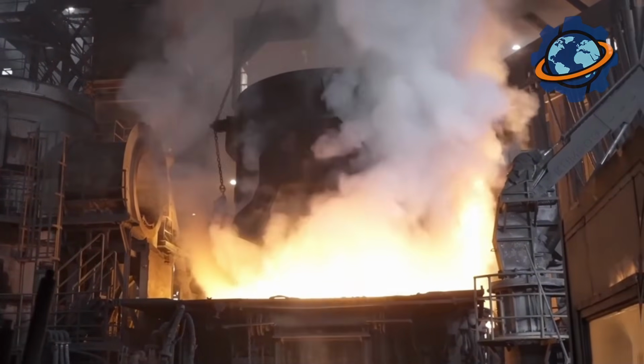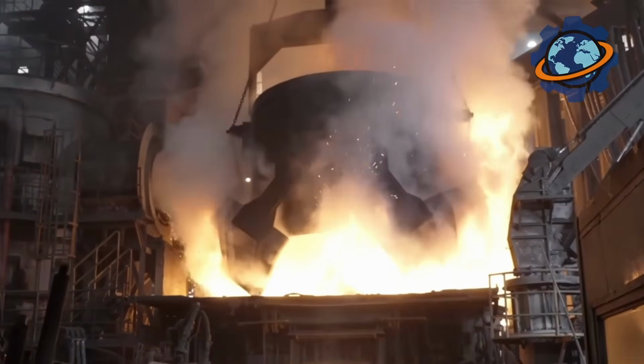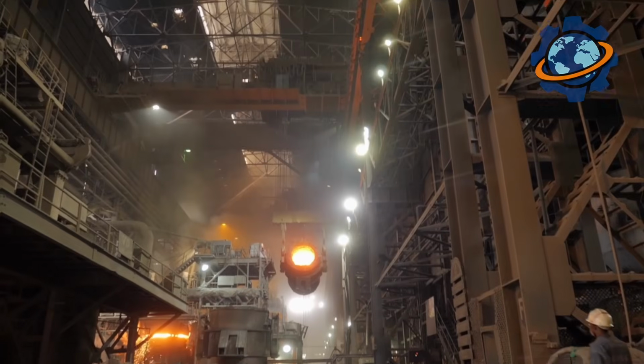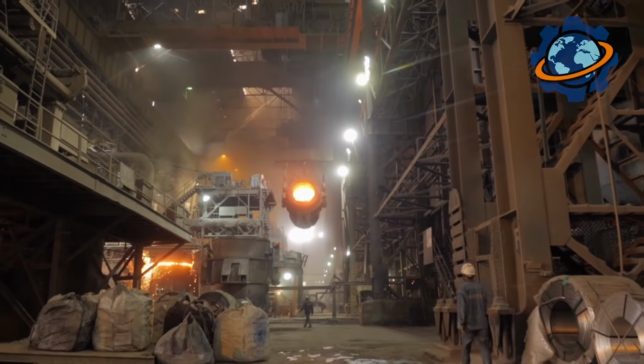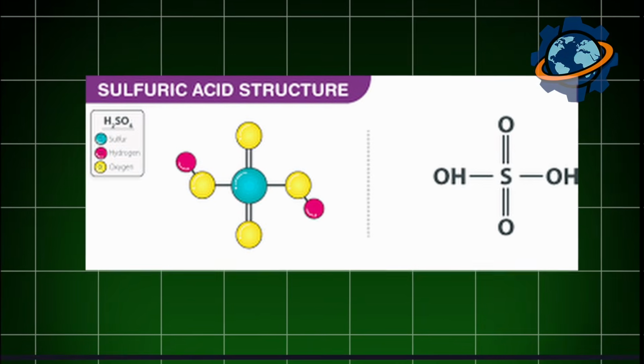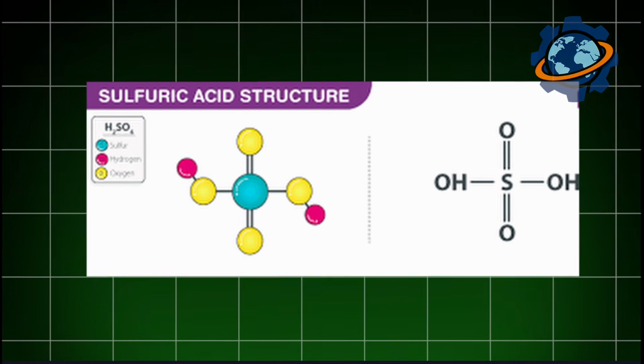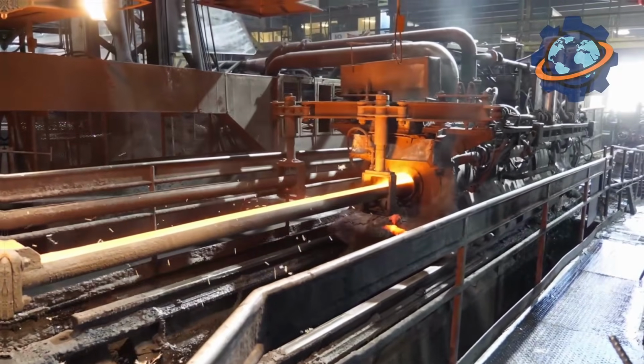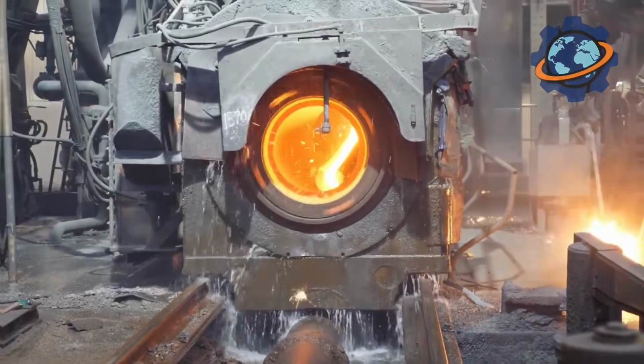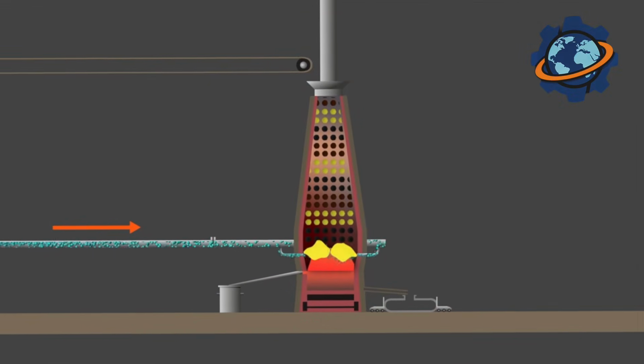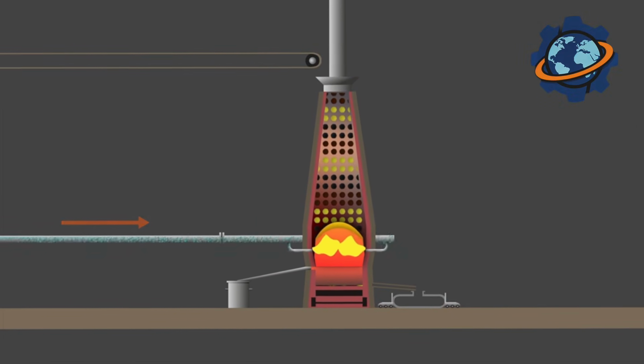Sulfur oxidizes, releasing enormous amounts of heat. Sulfur gas flies up the stacks. It will be captured and turned into sulfuric acid. And zinc sulfide transforms into zinc oxide, a gray-white powder. The temperature in the furnace is so high that the walls glow red. The roasted concentrate, zinc oxide, is cooled and mixed with coke, crushed coal. The proportion: 3 parts oxide to 1 part coke.